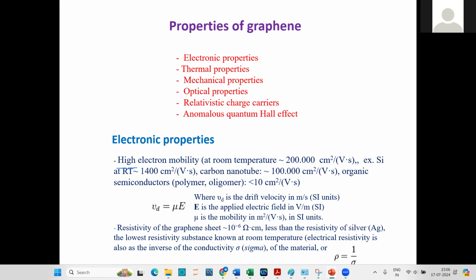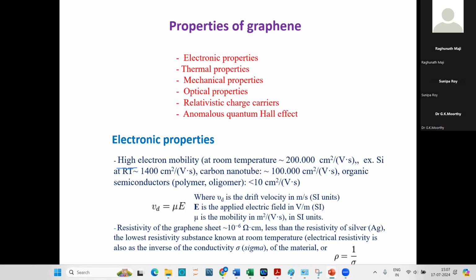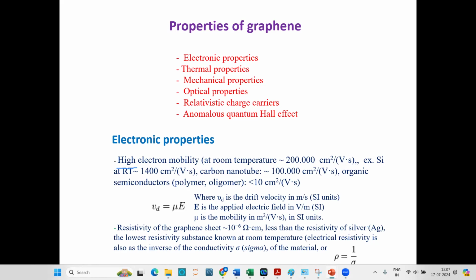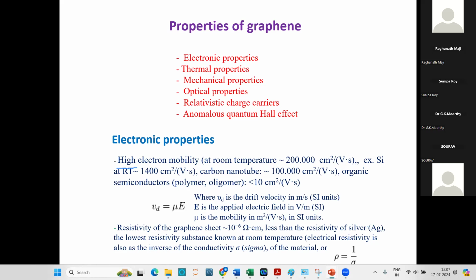Because if we add a number of functional groups to graphene, it becomes graphene oxide, and the forbidden energy gap, that is the distance between the valence band and conduction band, can be increased. So somewhere purity is not a blessing, it is a curse in graphene. Impurity is the blessing for graphene when we use it in a gas sensor, because the forbidden energy gap that was not present in pristine graphene can be introduced by using reduced graphene oxide. Now we can see the amazing properties of graphene: electronic property, high electron mobility, at room temperature 2 lakh centimeters square per volt second, whereas silicon has 1400 centimeters square per volt second.